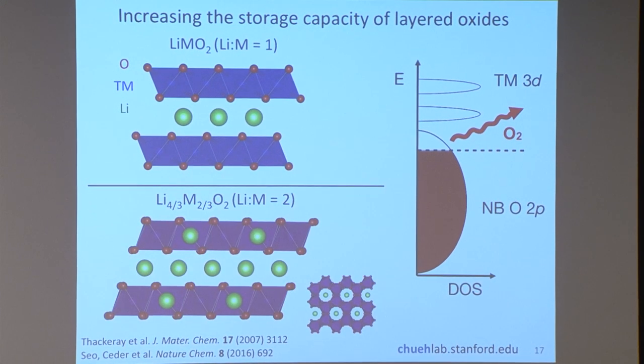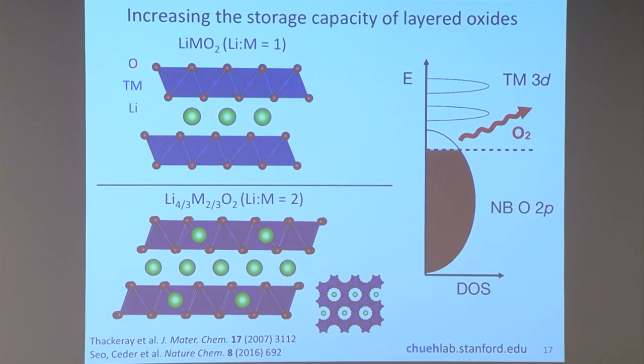One way that has attracted a lot of attention is to substitute some of the metal with more lithium. So this is called overstuffing of lithium. So some of the metal has been replaced with lithium. In the top example, the lithium to metal ratio is 1:1. In the bottom, it's 2:1. And the prevailing thought is that if you have this linear bond between oxygen and lithium, it actually keeps the oxygen intact. So this is the ionic bonding between lithium and oxygen. And this can somehow prevent the oxygen from leaving the material. And again, this would be necessary for preventing the rearrangement and the loss of the layer structure.